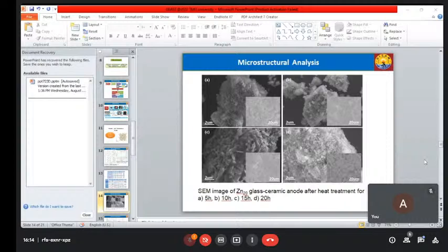So what were those phases? They are V2ZnO4, Na2ZnO2 and NaVO3. These three phases I have seen in my glass network after heat treatment. Some of these phases have a monoclinic structure, and one phase has a cubic structure.